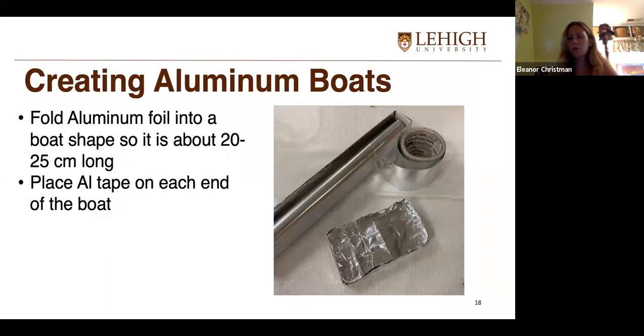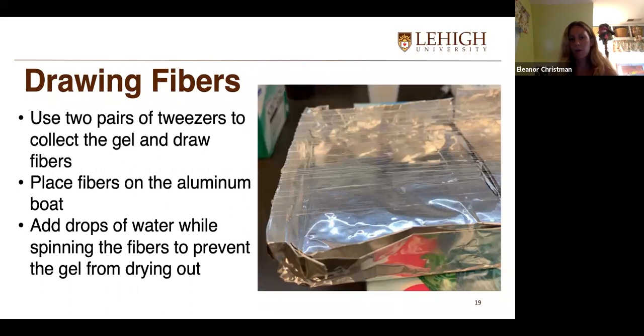So to start, I would always create these aluminum boats, which are just made of aluminum foil and aluminum tape, which is great because it goes straight into the cross-linking oven and doesn't contaminate my sample or anything. So I draw the fibers with 2 pairs of tweezers and place them onto these boats. And as I mentioned before, I add drops of water while I'm spinning the fibers to prevent the gel from